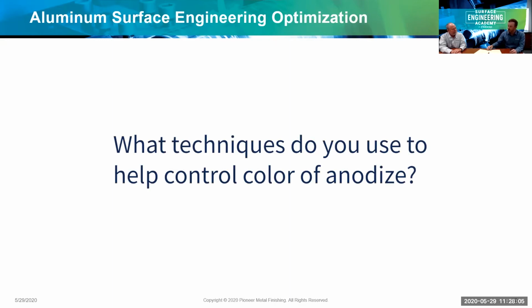Yes. Next question. Maintaining a consistent color seems to be a challenge for anodized product, dyed product specifically. What tactics does Pioneer employ to help control color? Well, you kind of have to go back to how do you make the part colored to understand how to control it. When we do anodizing, it's not like paint where you have an organic coating with a certain pigment to it and you're applying it over the base metal. When we make color anodizing, we take advantage of this aluminum oxide that we're forming having porosity, and we impregnate this porosity with a dye.